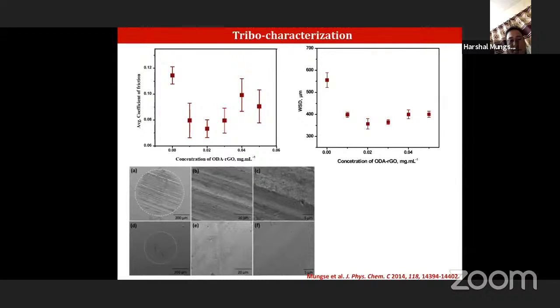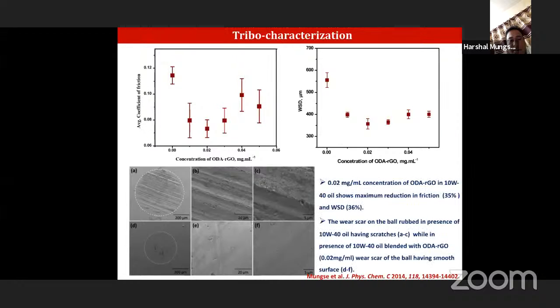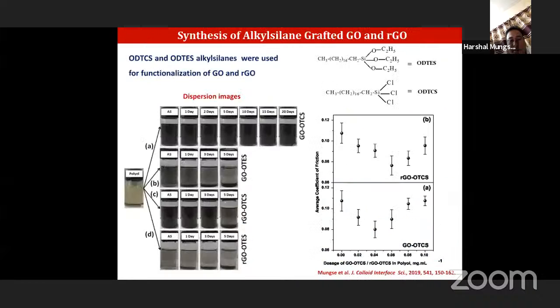You can see the upper images are in the absence of additive material, and the wear scar circle diameter is higher as compared to the lower images. The lower images are from when I used the functionalized graphene material as an additive. Then we can see there is no loss of material, and the surface is smoother. So it means the surface is smoother, friction is less, wear is less. Near about 36% WSD is reduced, and friction is also reduced by 35% in this case.